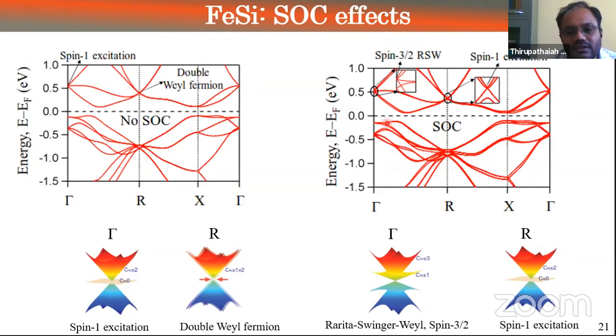But if you include the spin orbit coupling, now it changes. At the gamma point you do have in fact an RSW Weyl fermion instead of a spin 1 excitation, and at the R point you now have a spin 1 excitation. So from this study we understood that, especially when discussing these transition metal monosilicides, one should in fact consider the spin orbit coupling effects rather than just going without SOC.